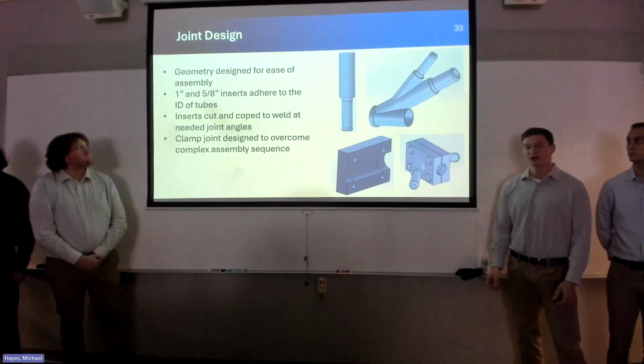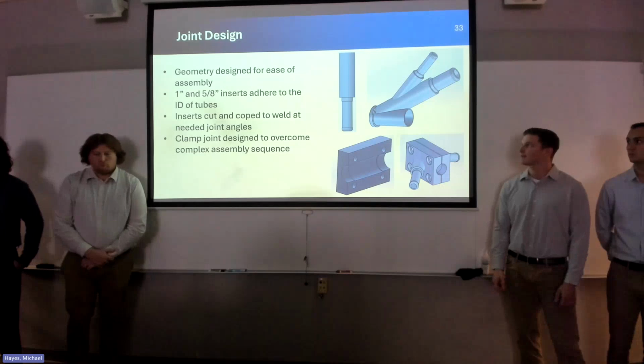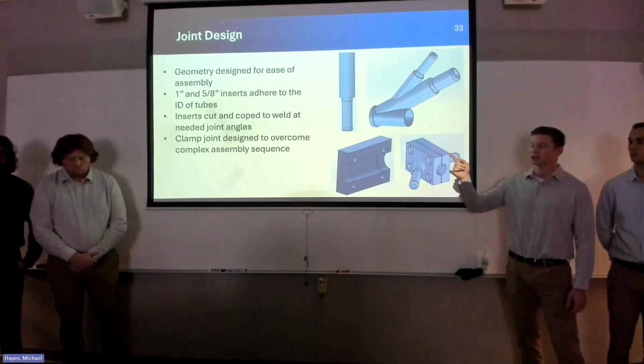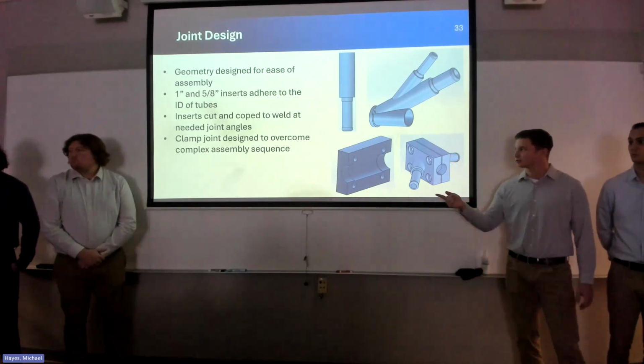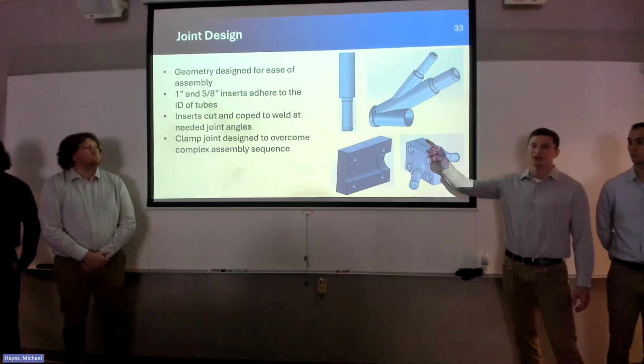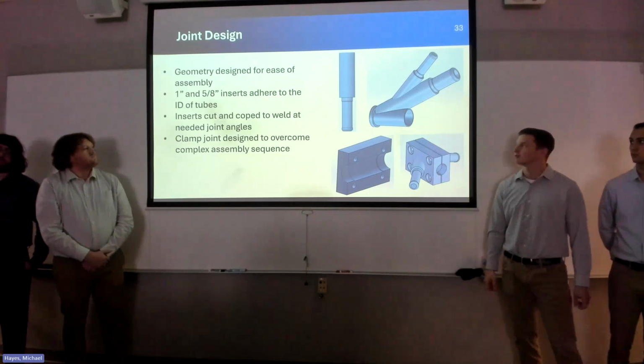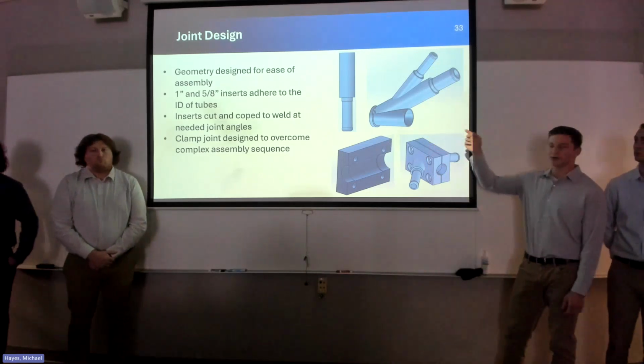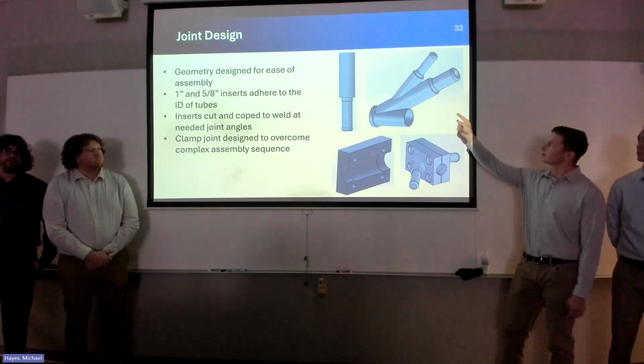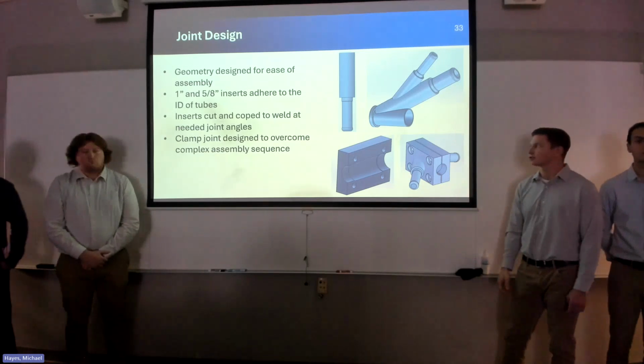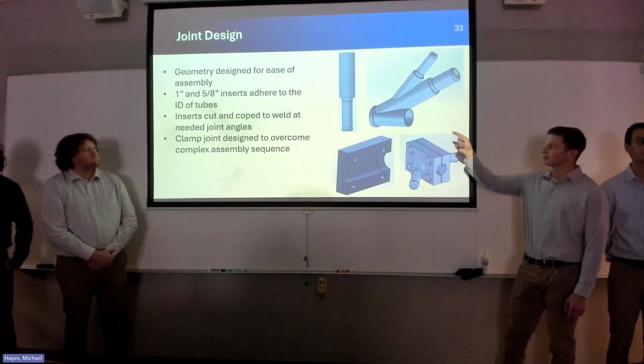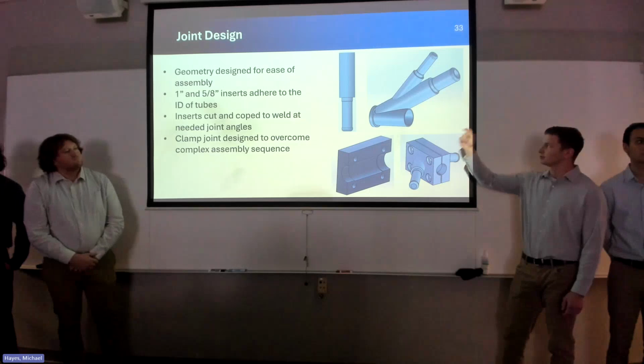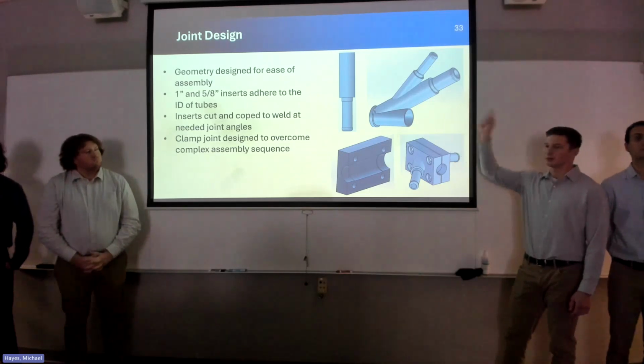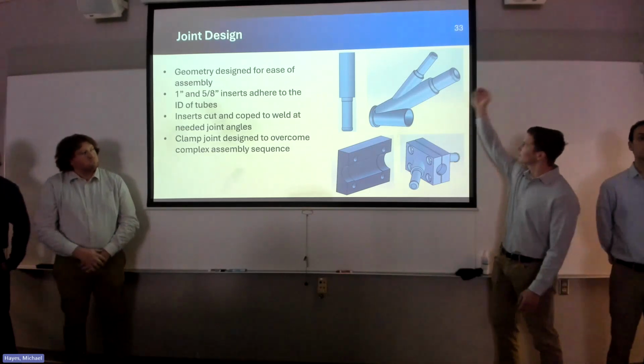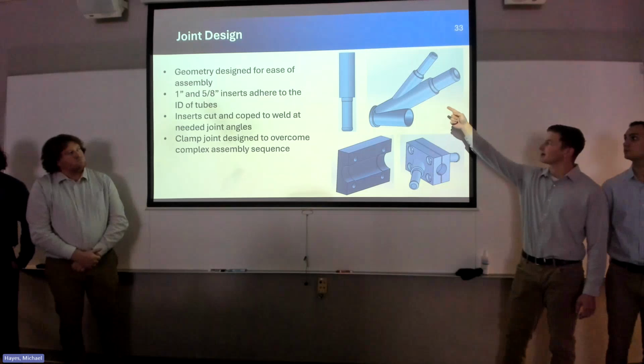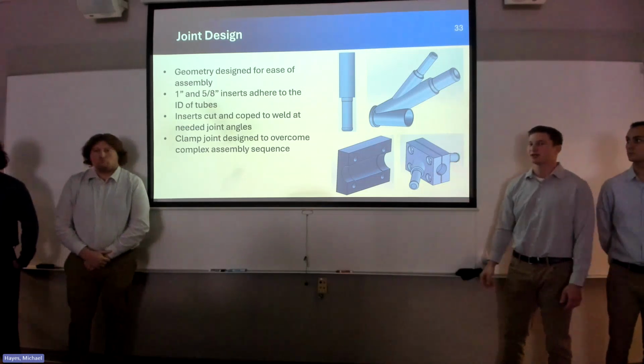As far as actually putting these to use in our truss design, we wanted to keep that 1 inch and 5/8 inch ID for those tubes. So we'll have 1 inch and then the 5/8 inch inserts, which we can then machine down as a coping and mount to pretty much any geometry we need. So in the upper right, you can see that this is the upper firewall mount. That would be bolted to the firewall. You would have a 1 inch tube coming off where that would slide in over this, be bonded there, and then a 5/8 inch there as well to be bonded in.